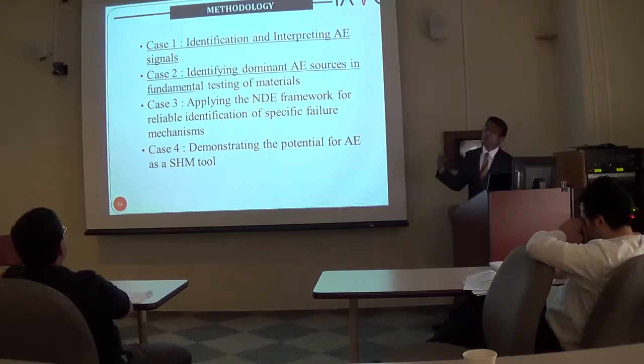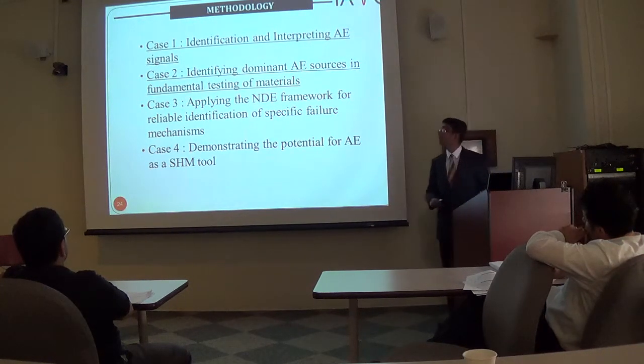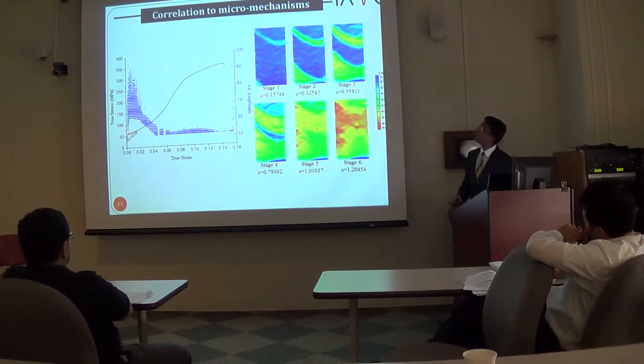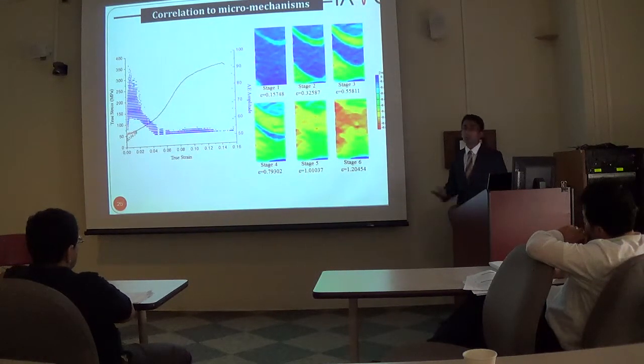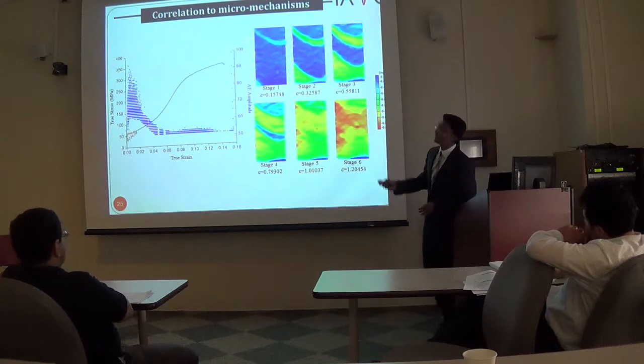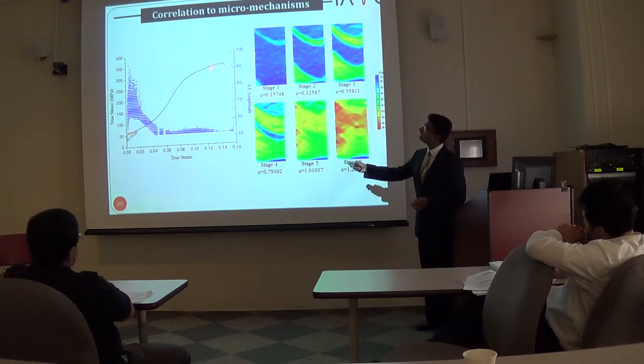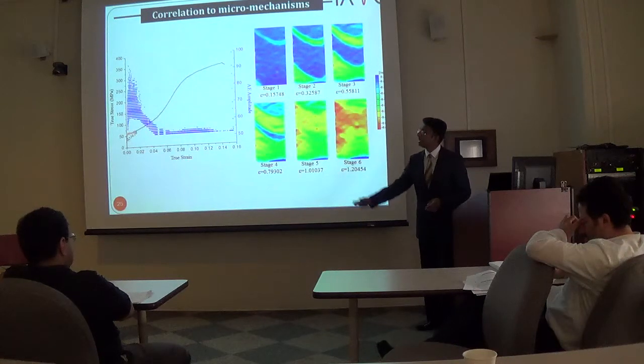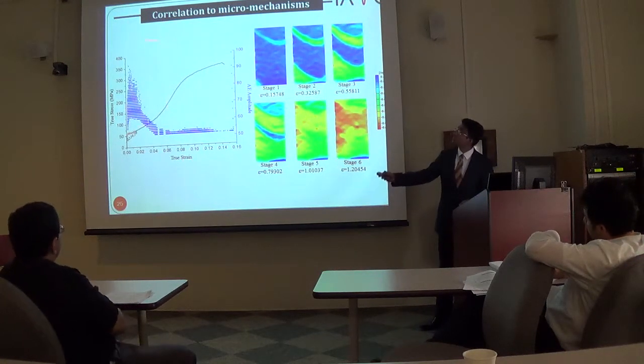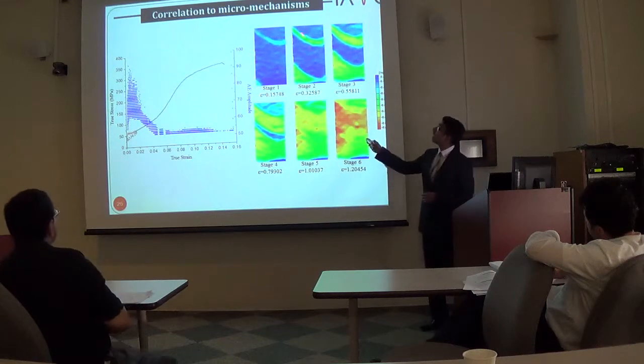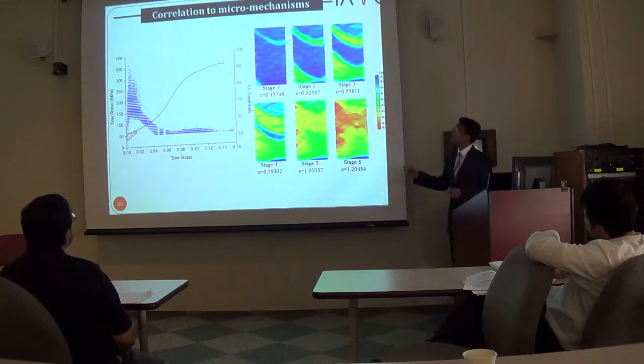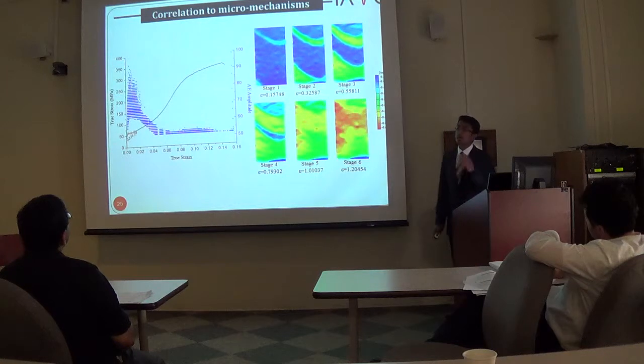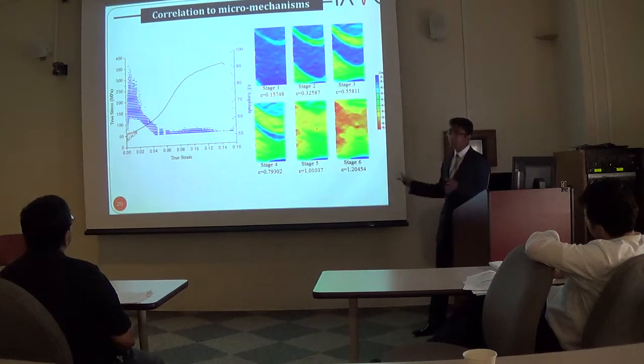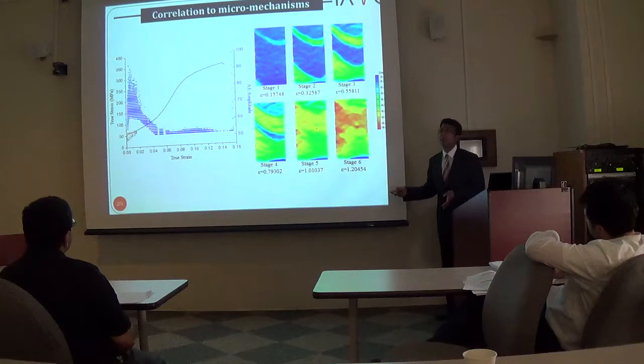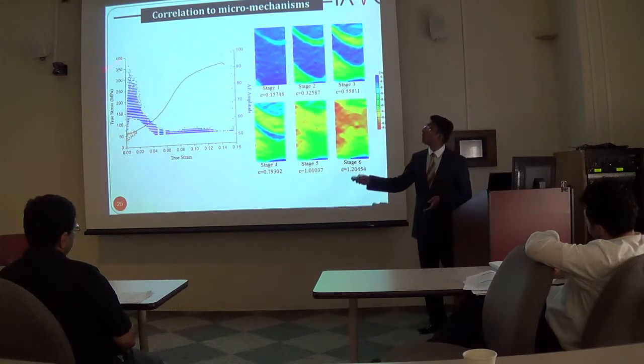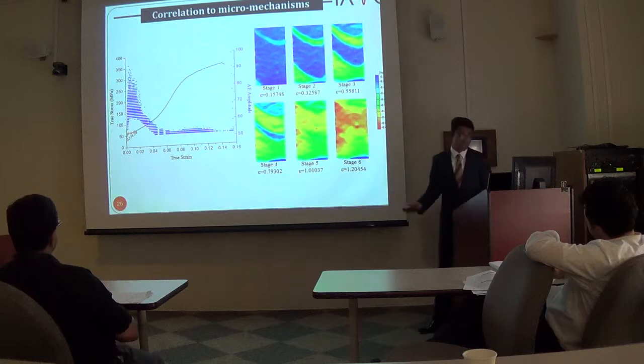So for this purpose, mechanical testing was carried out across different metallic materials, and the first test that was performed was with the AZ31 magnesium alloy. The compression specimens were tested until failure, but right around the point of yielding, we could see high amplitude signals which were coincident with localized strain bands that were formed at exactly the same time instance where high amplitude signals were detected. So the two independent techniques were seen to be in good sync and agreement, and revealed that this specific phenomenon was activated with this high amplitude.